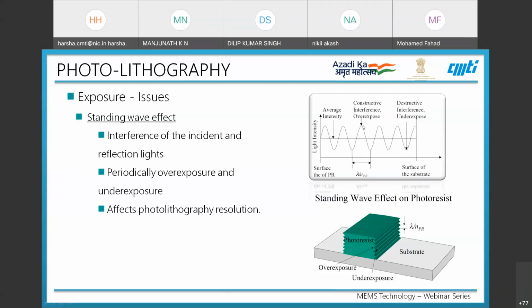At the peak, we have constructive interference of the incident and reflection lights, which leads to overexposure. At the valley, we observe destructive interference, which results in underexposure of the resist. Whether constructive or destructive interference, this results in dissimilar resolution, and we may not achieve proper resolution for the photoresist. You can see in the image the standing wave effect onto the photoresist, which results in overexposure and underexposure.